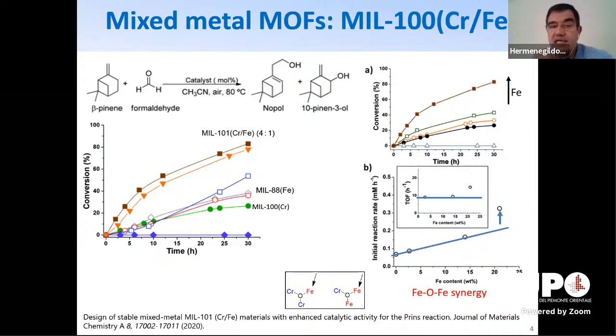And the answer is that we can have mixed metals, actually chromium and iron, where the chromium plays the role of providing structural stability to this type of highly porous MOF, while the iron provides the activity as the metal site. So when you have this MIL-101 chromium iron, the activity is much higher, and this is reproducible, because the reproducibility of the synthesis is quite high. This is actually one of the best advantages of MOFs, that the synthesis is highly reproducible.